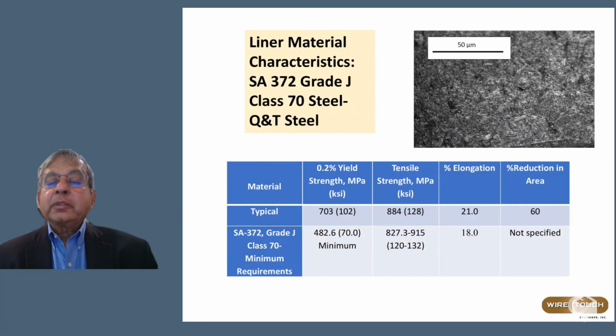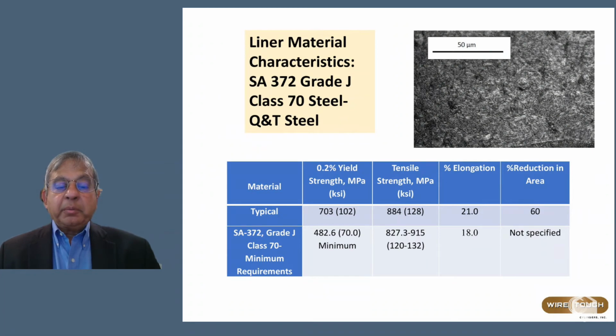Now, if we look at the microstructure of the liner material, which is SA372 grade J class 70 steel, it is quenched and tempered. The typical yield strength level is about 700 MPa. The tensile strength is on the order of 880 MPa. Percent elongation is 21%, and reduction in area is 60. And if you look at these properties compared to the standard specifications for SA372 grade J class 70 steels, the materials that we have used in deriving the properties under hydrogen conditions sufficiently exceed those properties. So they meet the minimum requirements.